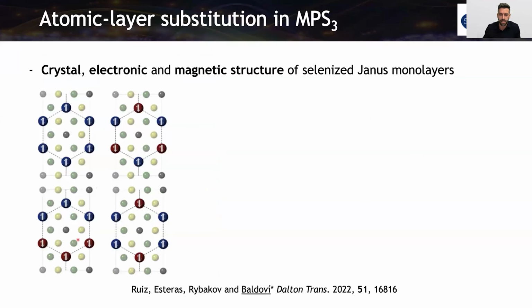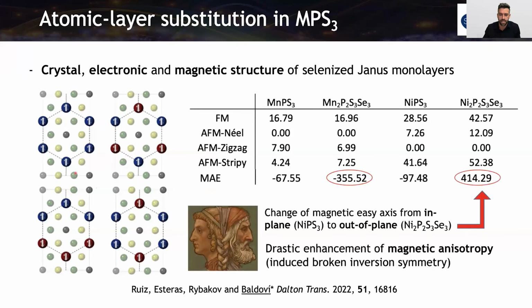Well, we have calculated for the different magnetic configurations. In all these cases, the effect of the Janus for the ground state remains the same. For example, manganese is a Néel antiferromagnet, and we have the minimum energy for the Néel. And in the case of the nickel, it is a zigzag. This is not changing, but the magnetic anisotropy energy is changing drastically.